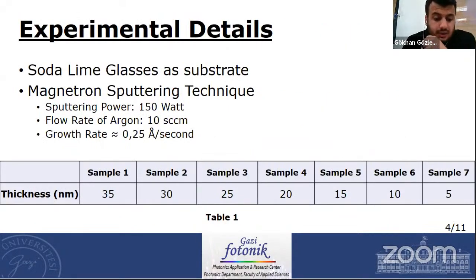As for the experimental part, in this study, we used soda-lime glass as substrates. Glasses were cleaned with soap and isopropyl alcohol, then dried with nitrogen gas, and loaded into the magnetron sputtering system. After the evacuation of the system, titanium dioxide thin films were deposited on glass. During deposition of all samples, sputtering power was 150 watts, flow rate of argon was 10 sccm, and grow rate was around 0.25 angstrom per second.